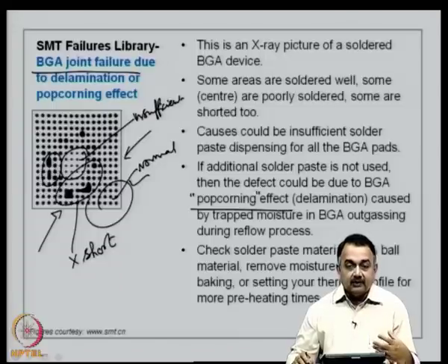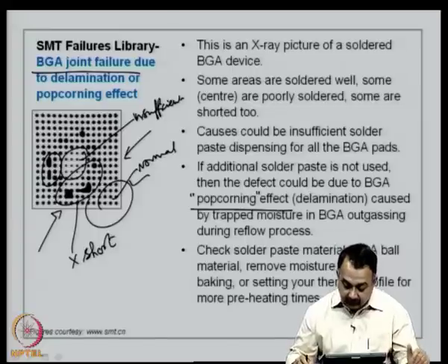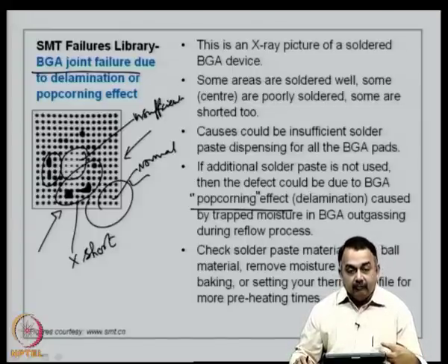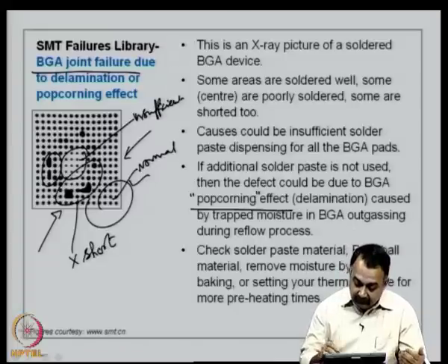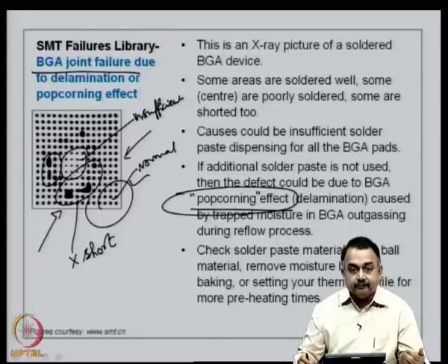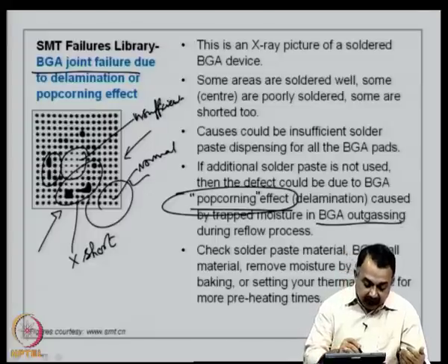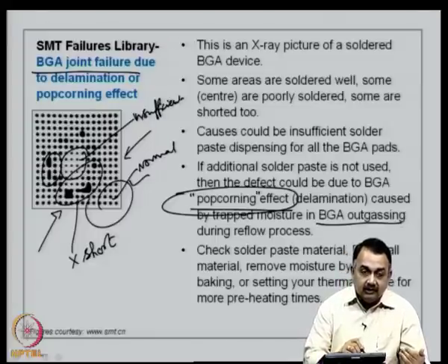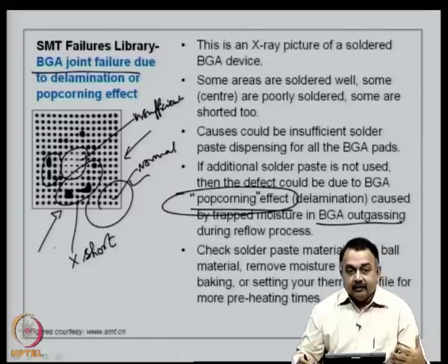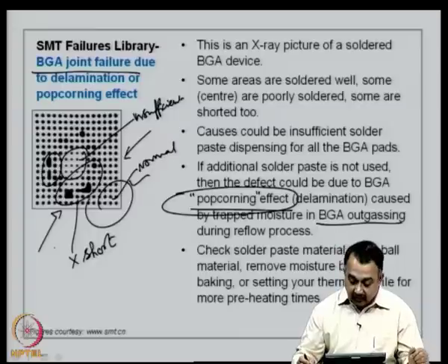Okay, epoxy, as you know, is well known for its moisture absorption, and before you are doing the process, you have to do a pre-bake. If you have not done a pre-bake, then you will see this kind of a popcorning effect. Okay, so avoid BGA outgassing, because it is very difficult to desolder a BGA and then repair at that particular site. It is very easy to do a repair for a through hole component or an SMD device, but if it is a large pin count BGA, then you have to spend a lot of time on reworking the device.